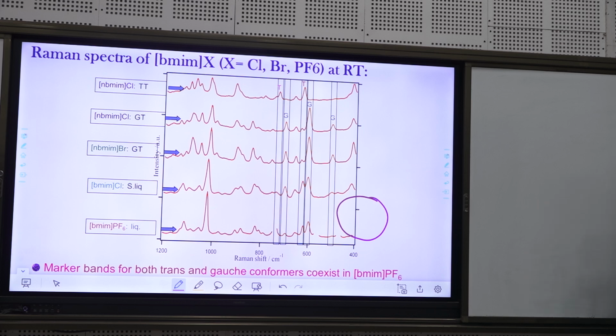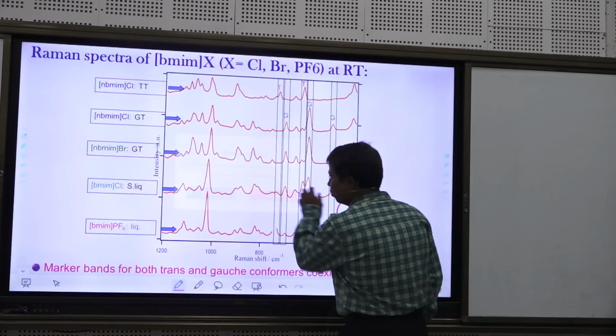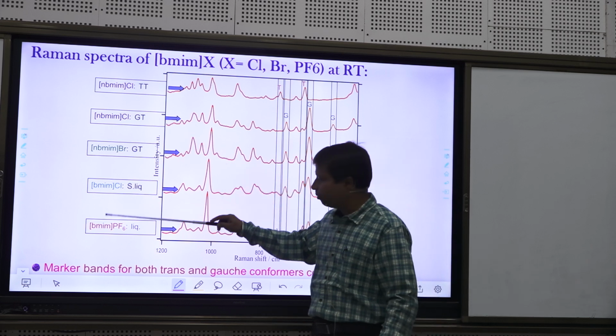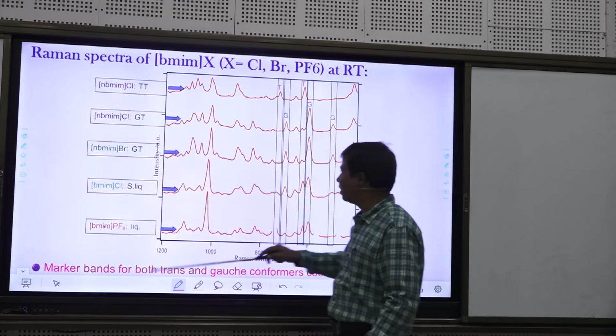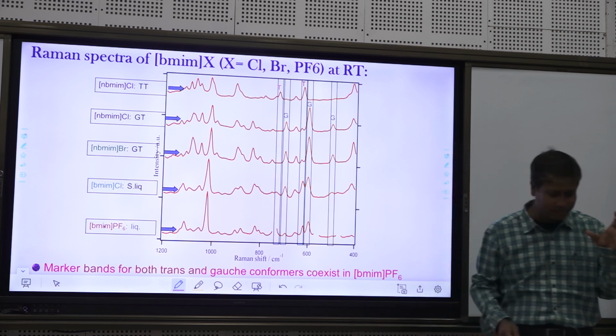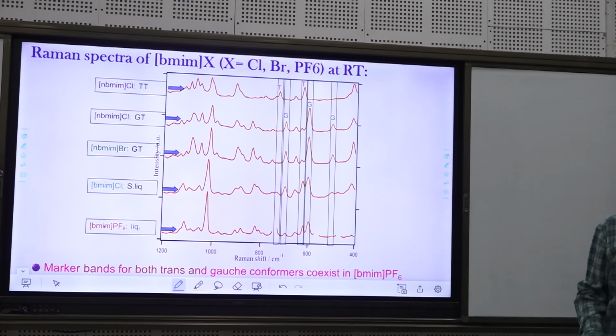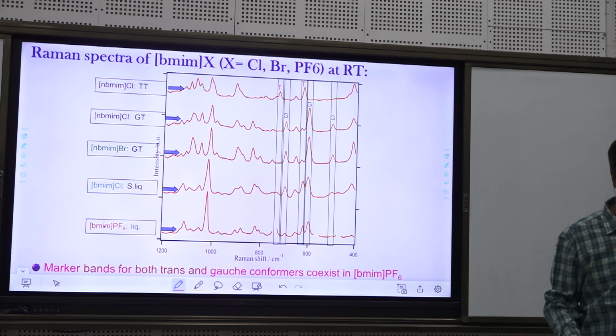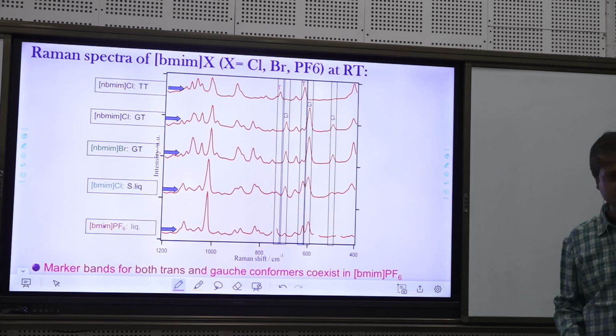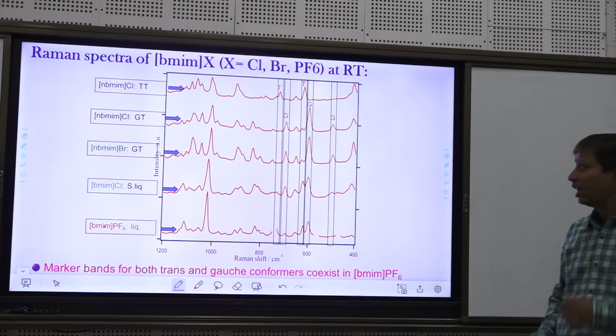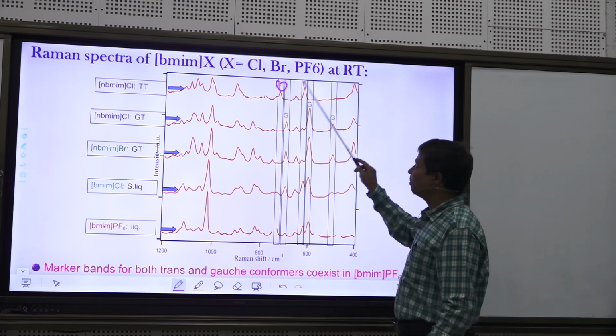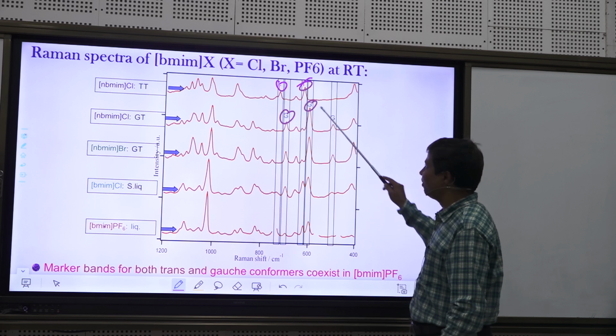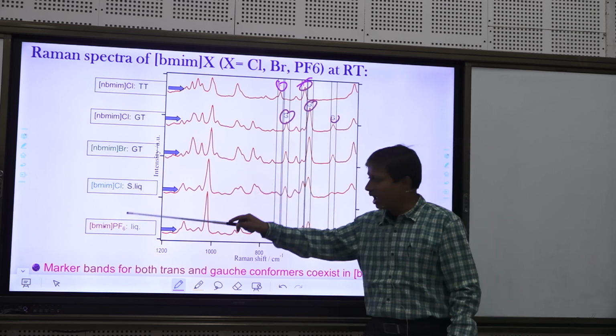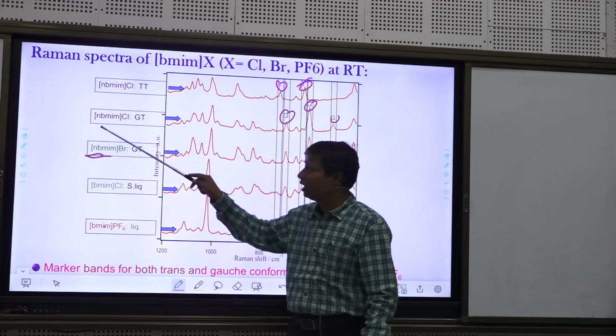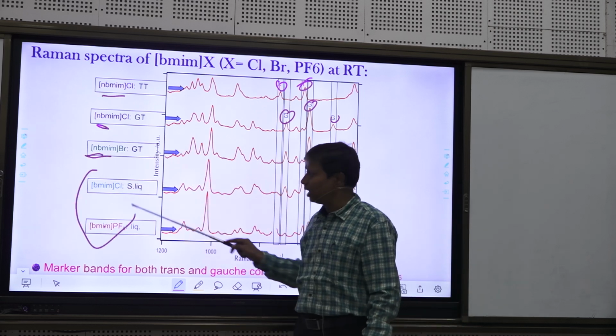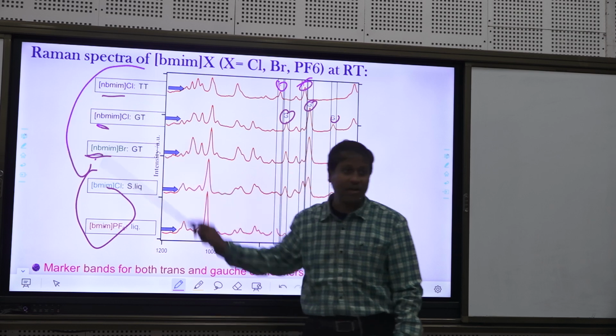Now, to establish this hypothesis, we have taken various kinds of ionic liquid, and we found marker bands. A marker band means that if a particular band appears in your spectrum, by seeing its appearance you can tell whether the molecule is in trans conformation or gauche conformation. This marker band, whatever we have identified, is found to be applicable in another set of molecules, N-BMIM. So we started with BMIM, and we have proved our theory for another set of compounds.